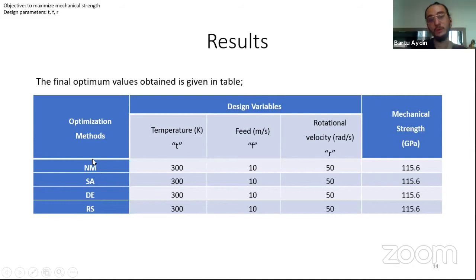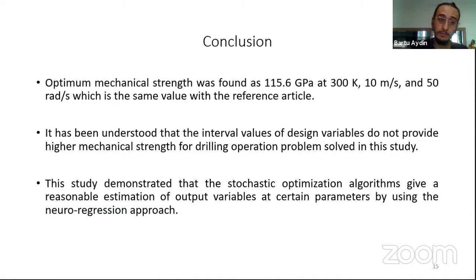Okay. We carried out the methods Nelder-Mead, simulated annealing, differential evolution, and random search. These algorithms work independently of each other, so we can interpret obtaining the same values in all algorithms as them being global optimum values for this study. Consequently, the optimum mechanical strength was found as 115.6 gigapascal at 300 Kelvin, 10 meters per second, and 50 radians per second, and these values are the same as in the reference article.